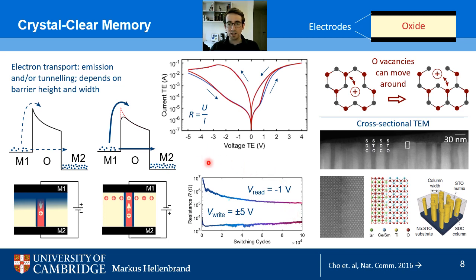And the combined conduction of oxygen vacancies and electrons can be illustrated in a more complete figure here, where we measure the total current on one of the contacts as a function of the applied voltage. So if we apply a positive voltage on the top contact M1, it means that we move away the oxygen vacancies, so they accumulate on the other side on M2. This means we lower the barrier, we get a higher current. If we then go to negative voltages, first we still have the high current, but with increasing negative voltage, the oxygen vacancies are again drawn towards the contact M1, and this means the barrier will be increased, and consequently the current when going back will be lower. So this would be the total picture of the switching.